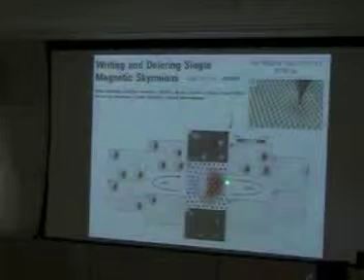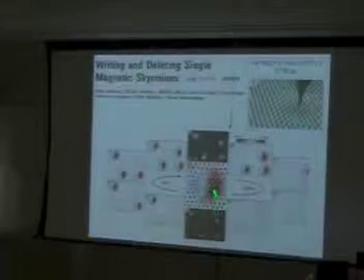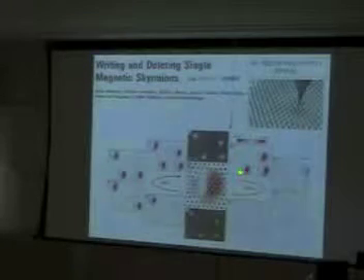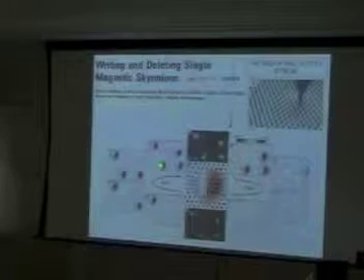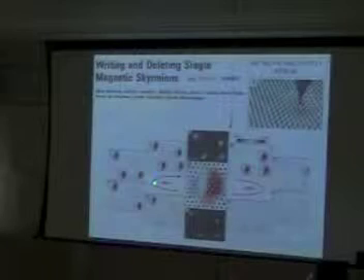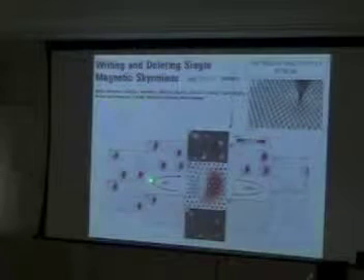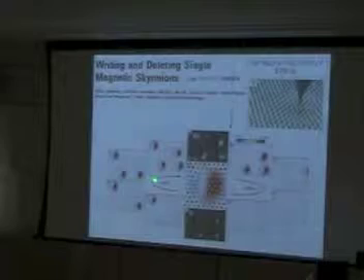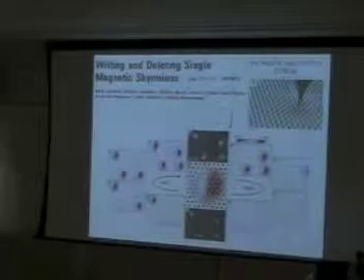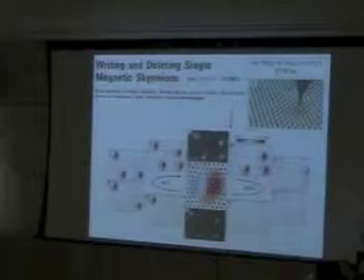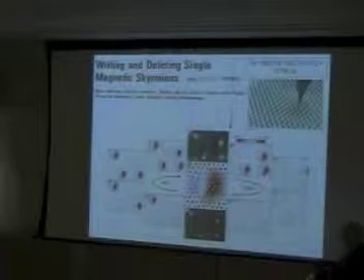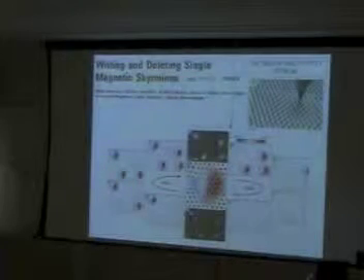What is also interesting in the results of this paper is that this creation is always easier on some defect of the magnetic layer, some adatom or vacancy. This confirms that defects can play an important role. When you have a topological barrier, if there is some defect, the path is lower at some point.